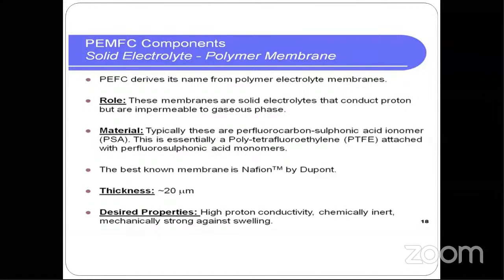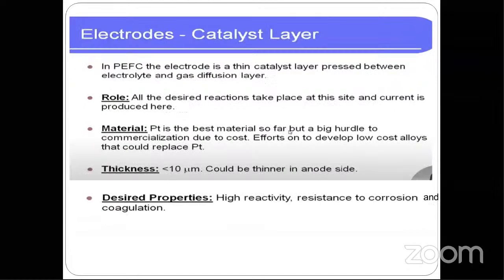If you see the materials we are using here, we are using perfluorocarbon sulfonic acid ionomer. Basically, these are called Nafion membranes. Nafion is the best known membrane till now, produced by the DuPont company. The thickness is very small, 20 microns. The desired properties for the electrolyte are, as I said, it should conduct the protons efficiently, it should be chemically inert, and it should be mechanically strong against swelling. So this is the basic function of the electrolyte.